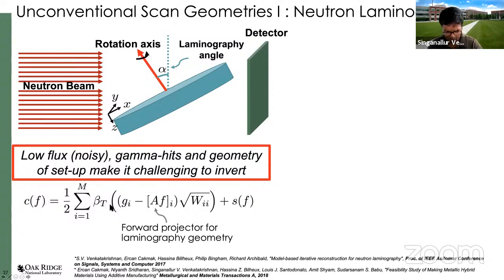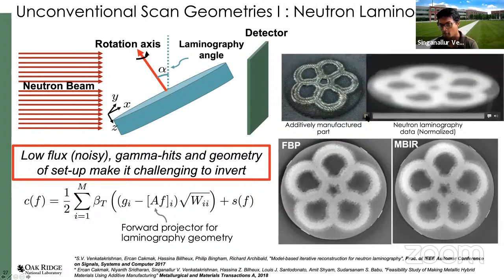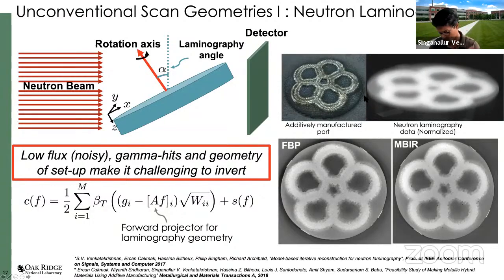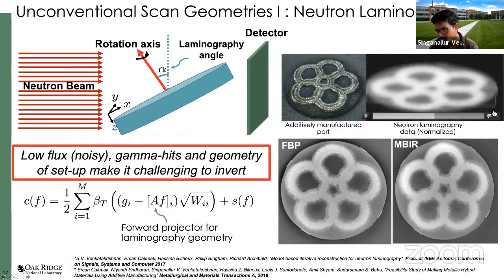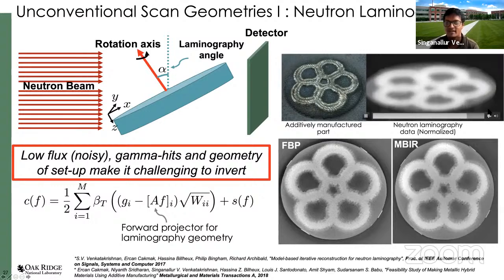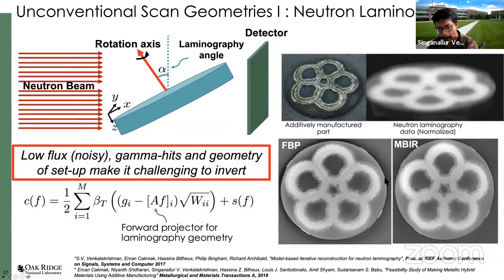to allow for different forward models and geometries. Once again, the forward model is similar to the previous example, but in this case, we have designed a different forward operator, which can allow for these complicated geometries. So now it allows scientists to do different things. Here is an example of some results of an additively manufactured part of cobalt chromium measured at a neutron beam line. What you're seeing is that the part is taped, and neutrons are able to discriminate, for example, the tape. Anyway, that's the data. And here is a cross-section from the filtered back projection and the model-based approaches. You can see that it has lower noise, and you're able to resolve pores. In this case, they were interested in studying defects in the sample. So by using these model-based methods, it's easy to now orient your sample differently, and that expands what you can do at an instrument compared to before.